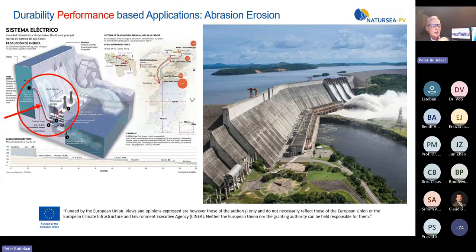The entrance to the inlet was only possible by entering a small manhole, and Edelca decided to anchor and weld small steel plates on the existing steel lining, with the consequence that the extremely fast-flowing water containing abrasive particles removed the anchored and welded plates very fast and destroyed the turbines.